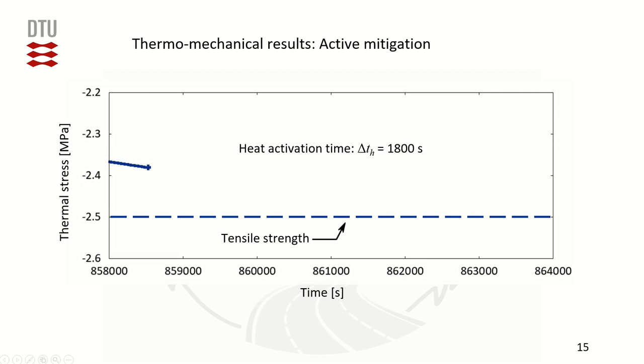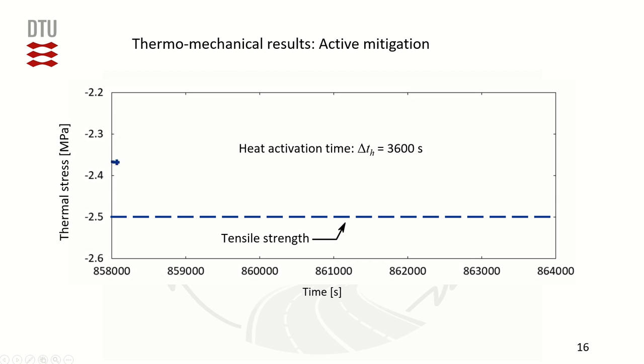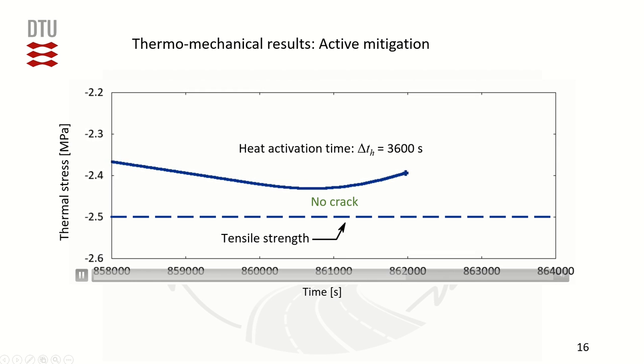With the focus set on the same time span as on the previous chart, activating the heating 1800 seconds prior to cracking is sufficient to avoid the low temperature failure. Finally, since 1800 seconds was sufficient to mitigate the cracking event, 3600 seconds is as well. During these 6000 seconds, compared to an activation timing of 1800 seconds, a timing of 3600 seconds results in a minimal thermal stress value occurring 1680 seconds earlier.